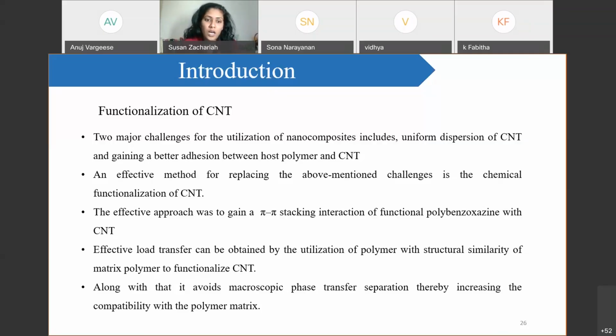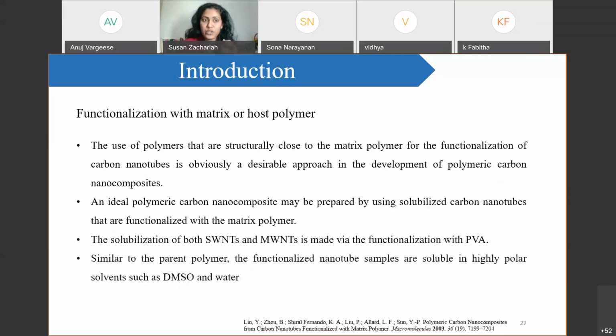So what we have done is functionalization of the CNT with the matrix or host polymer. We were thinking of making it disperse properly and get good adhesion with the polymer, so why can't we use the same polymer to functionalize the CNT? Here, the matrix polymer itself is used to functionalize the CNT.